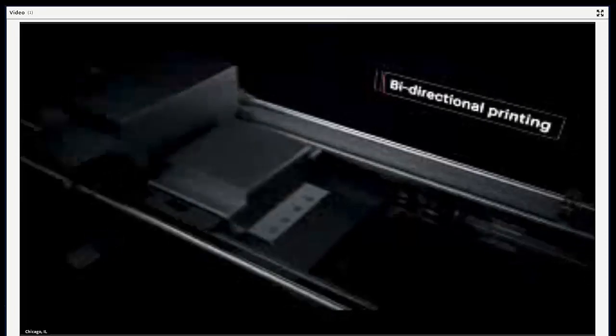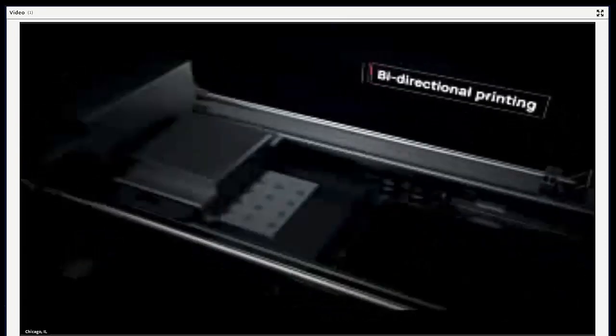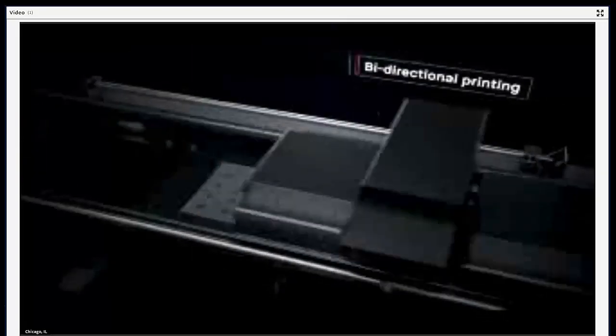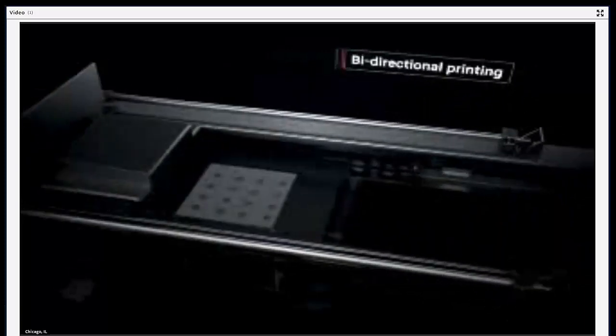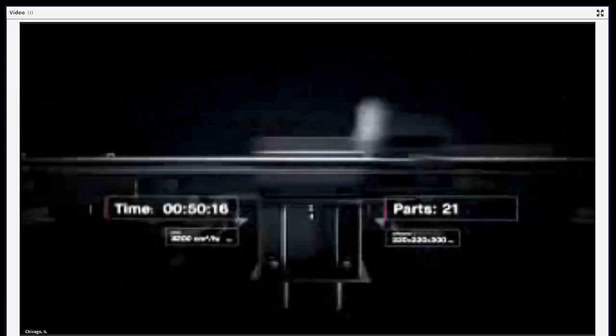Anti-sintering agents are then deposited, making it possible for supports to fall off after sintering, saving hours of post-processing. Once the layer is dried, the process repeats itself. Single-pass jetting is bidirectional. We combined all the necessary steps for printing into a single pass, so that whenever there is movement, there is printing. This makes it possible to print parts in minutes instead of hours.